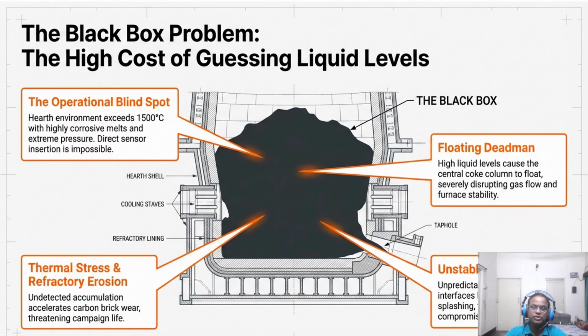So look at the cross section on the screen. When we guess liquid level, we risk the black box failing us in three ways. We get a floating deadman which disrupts gas flow, undetected refractory erosion that threatens the entire campaign, and unstable tapping that leads to dangerous splashing at the tap hole. So guessing is very expensive and it's dangerous also.